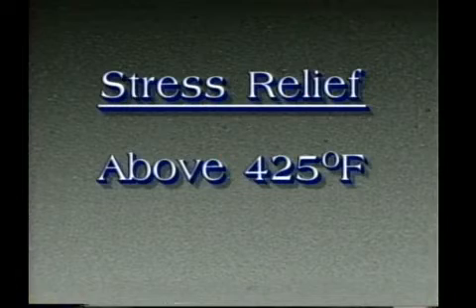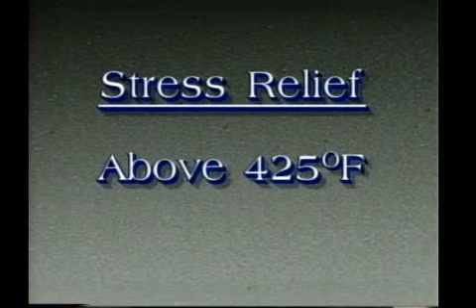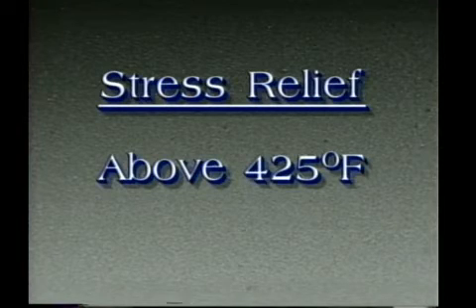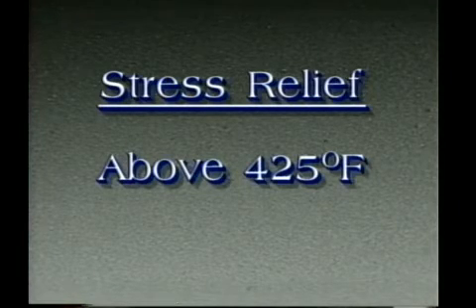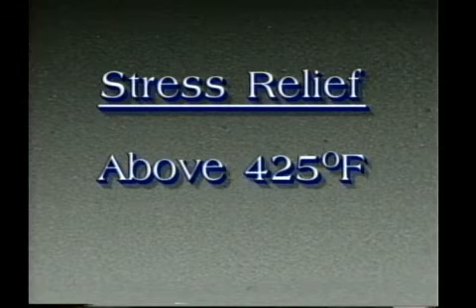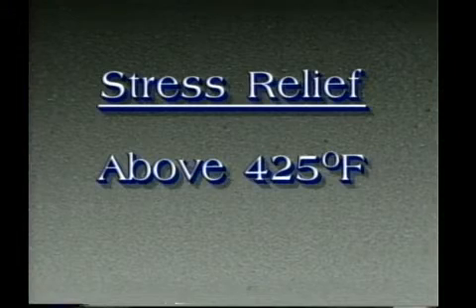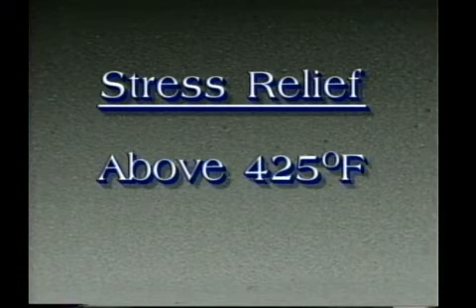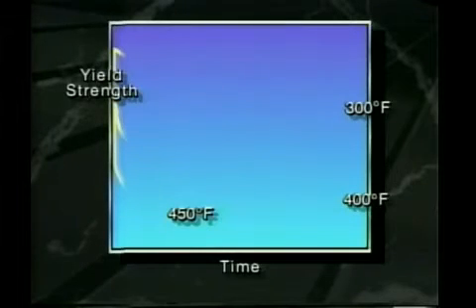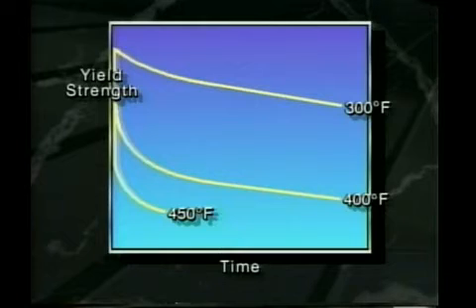Let's now review low-temperature stress-relieving operations. Effective stress relieving of aluminum alloys is only accomplished at temperatures usually above 425 degrees. This is due to the fact that in order to thermally reduce residual stresses that are generated by forming or welding operations, the yield strength of the material must be reduced. Unfortunately, in order to significantly reduce the yield strength of aluminum alloys, the temperature must be raised above 425 degrees. And unfortunately, most aluminum alloys are aged at temperatures below 425. Thus, stress relieving at higher temperatures will seriously lower the properties.